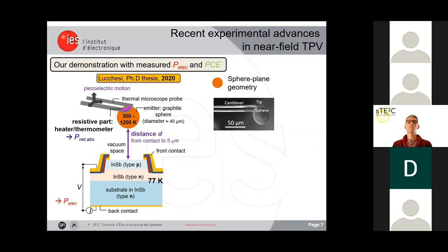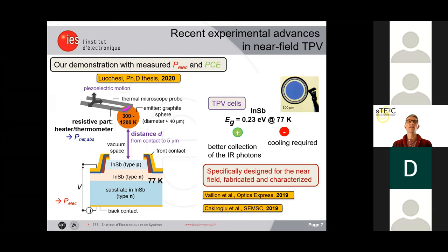In our experiment, what we use is a graphite sphere, which has a diameter of 40 micron as the emitter, which is attached to a thermal microscope probe. And at the tip of this probe, we have a resistive part, which is used as the heater and the thermometer. And with this, we can measure the variation of the net radiation power absorbed as a function of distance from contact to 5 micrometers. As for the TPV cell, we choose indium antimonide, which has a very low band gap of 0.23 electron volts, which allows a better collection of the infrared photons. However, like many infrared detectors, we had to cool down the TPV cells to 77 Kelvin.